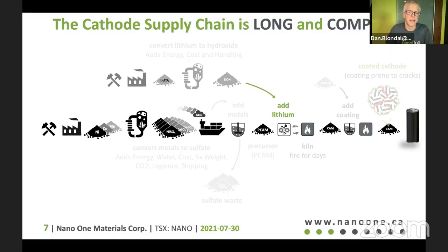mixture. And once you have that powder mixture, it goes into ceramic trays, and it's conveyed through very large, long furnaces. They're like big, long pizza ovens, and they're pushed through these furnaces at up to 800 to 900 degrees Celsius. At that point, the lithium melts into the PCAM powders, and lithium starts to work its way between all the nickel, manganese, and cobalt atoms to form the crystal structures that will then allow it to be charged and discharged in a battery.